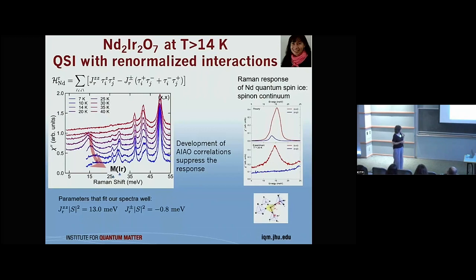So the lower we go in temperature, this mode appears when iridium is ordering, and then as soon as we start to develop all-in, all-out correlations between neodymium, it shifts to high frequencies, broadens, loses intensity, and basically disappears. So what comes out of this model is that this mode is basically a collective mode from the spinon continuum in this quantum spin-ice. And then as soon as we start to get all-in, all-out correlations between neodymium spins, the coherence gets pulled and it disappears.